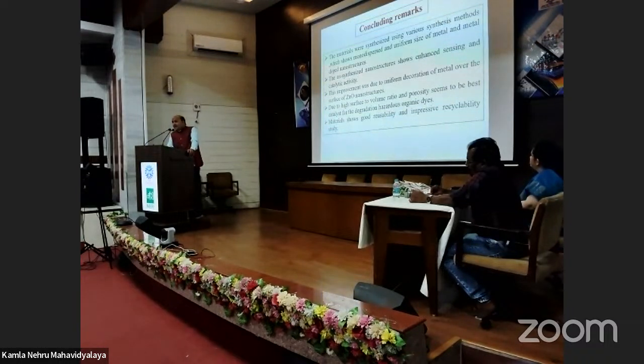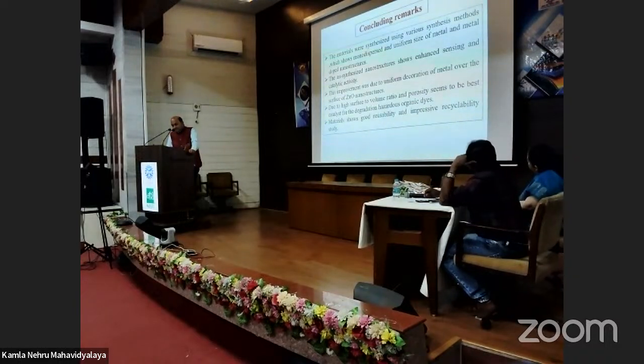So finally, I would say that the material can be utilized as a gas sensor, for heterogeneous catalysis as well as a photocatalyst for the degradation of dye, for the betterment of organic transformation reactions, and for sensing with the selectivity study. Due to the high surface to volume ratio and porosity, it is a very good material for degrading hazardous organic dye. The material shows good reusability and impressive stability.